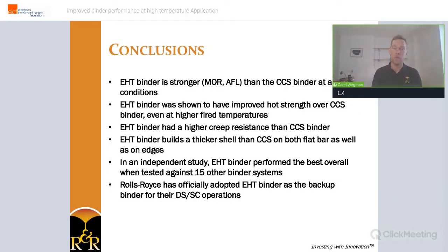So the overall conclusion: EHT binder builds shells that are stronger than the CCS, the commercial colloidal counterparts, in green as well as post-fired. Generally speaking, increasing the firing temperature from 900 to 1350 degrees C increases the hot strength when tested at 1200 degrees C, but it decreases when tested at 1450 degrees C. Nevertheless, EHT binder outperforms the CCS binder regardless of the firing temperature and testing temperature.